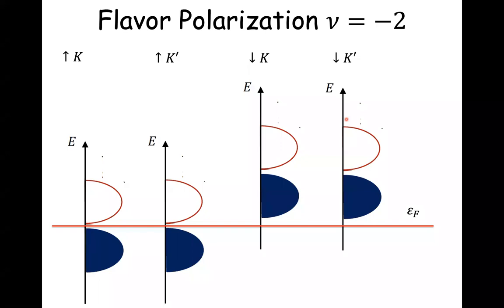And there's another important change, which is summarized on this slide. So this is a cartoon of the flat valence band in blue and the flat conduction band, the two flat bands. There are four of them, one for each spin and valley. What I've said so far is that you can open up a gap between the valence band and the conduction band. And when you do, you get a Hall conductivity.